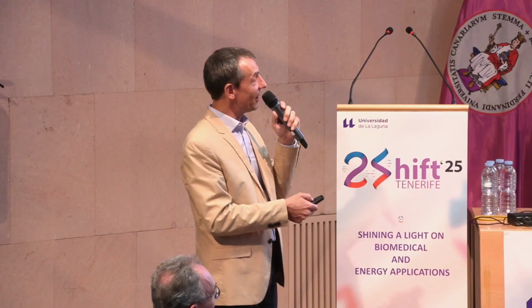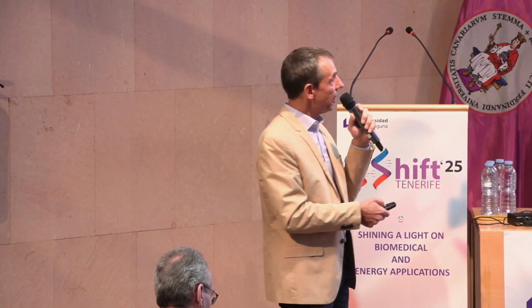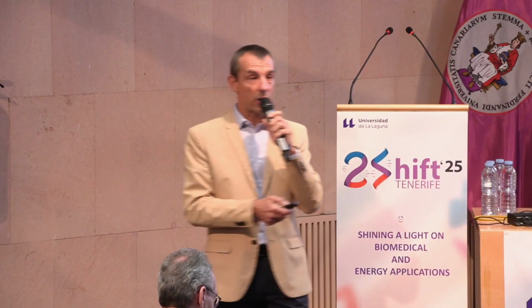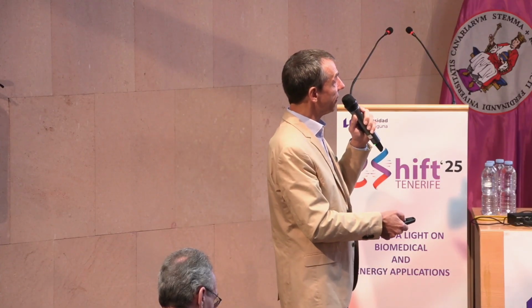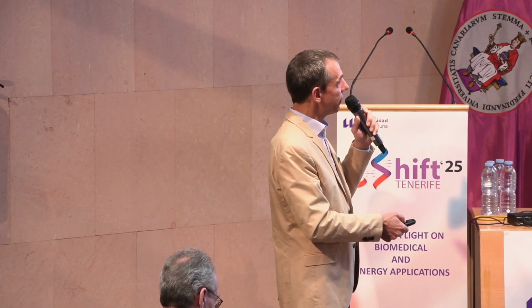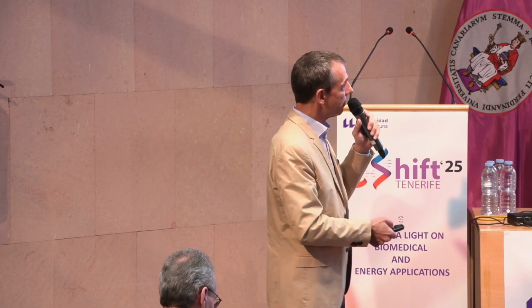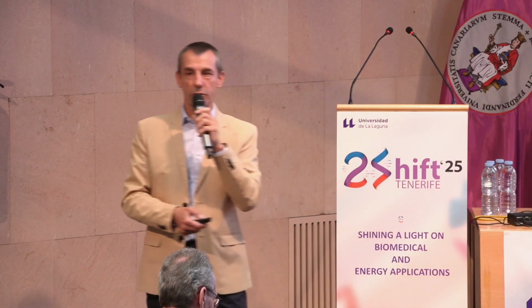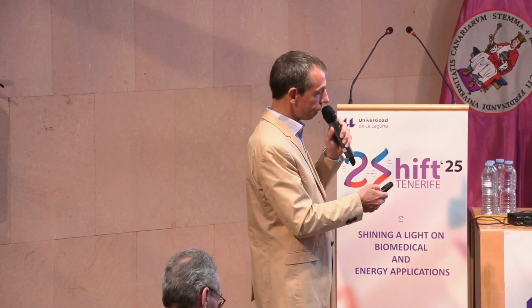And also, a very nice feature of rare earths is they also have electron and/or nuclear spin transitions. And so we can really realize this scheme. And in this case also, you can observe very long quantum state lifetime for this spin transition. And in the case of nuclear spins here, this T2 can reach up to several hours. So really a long time to do processing and storage.